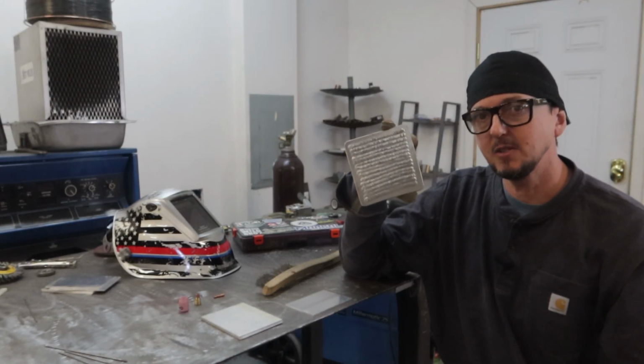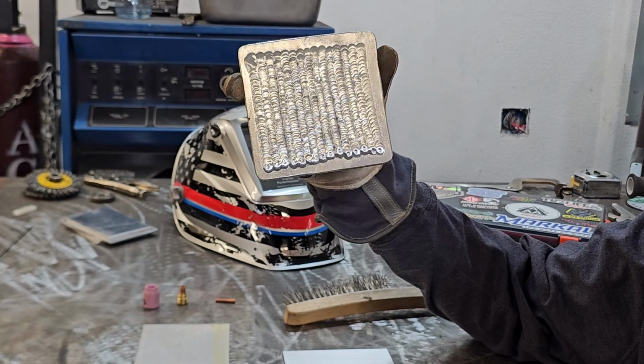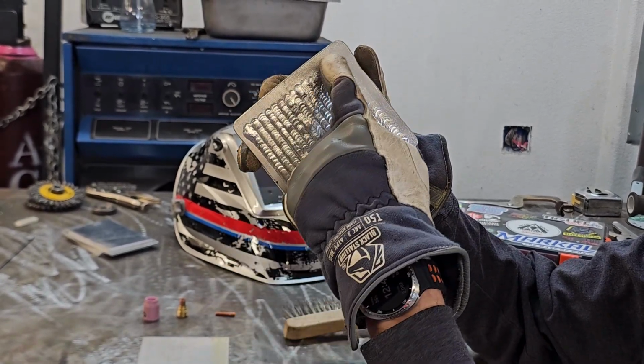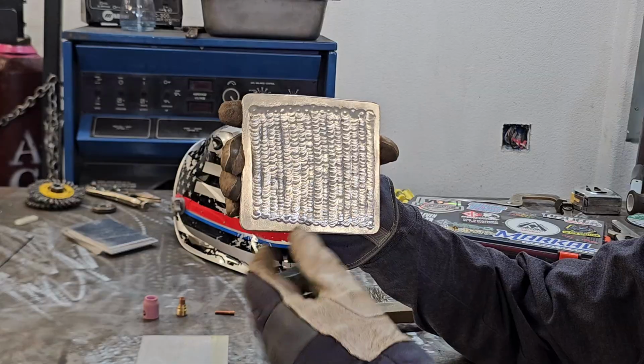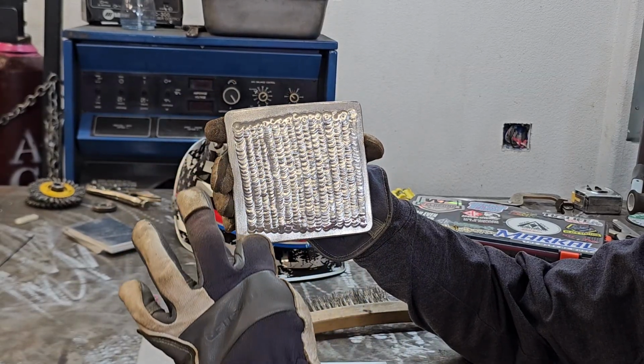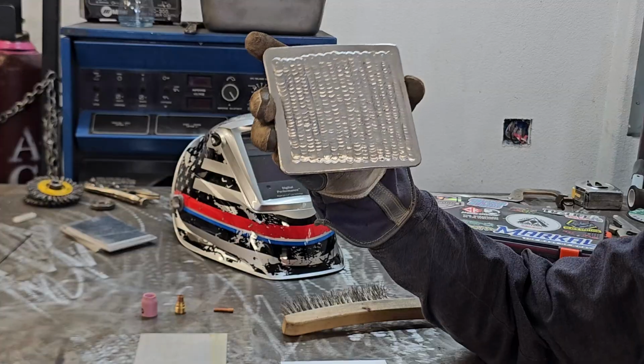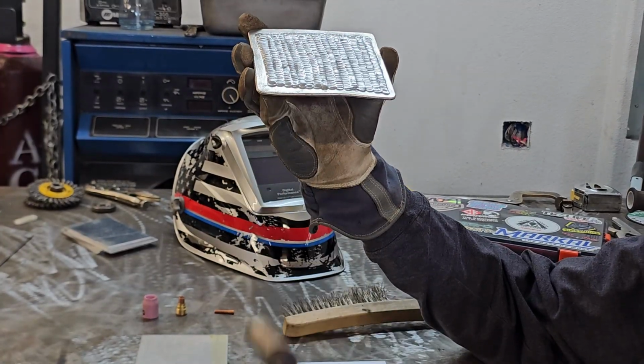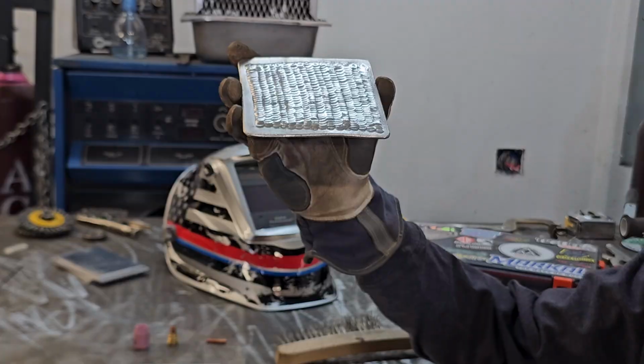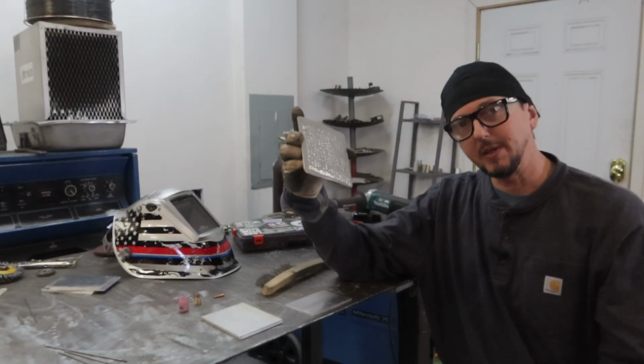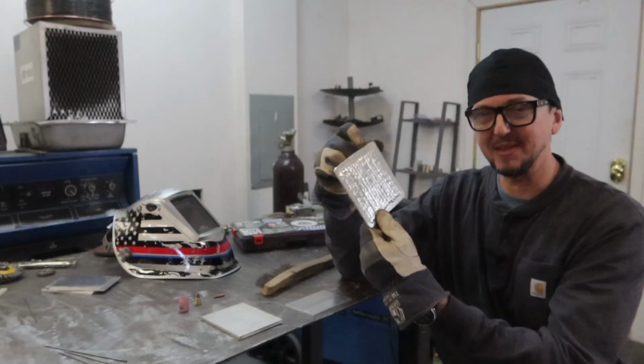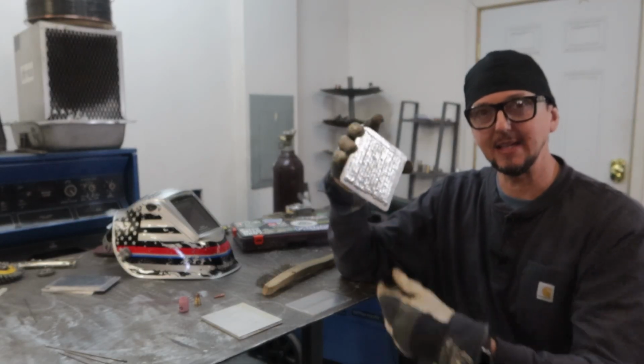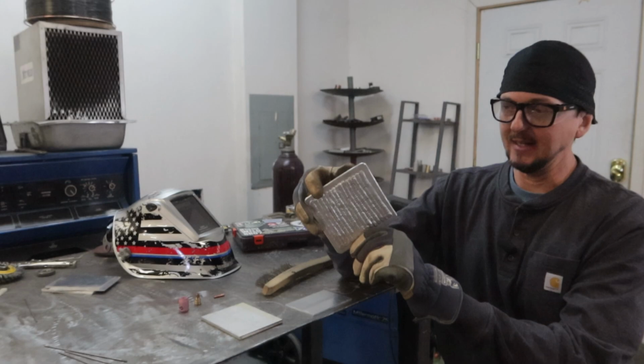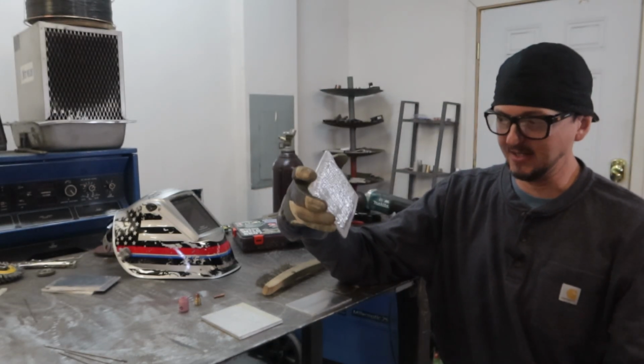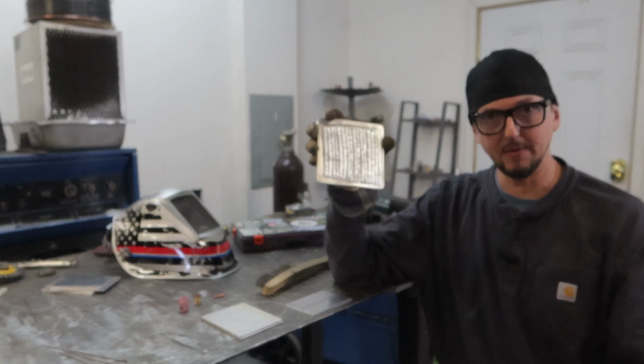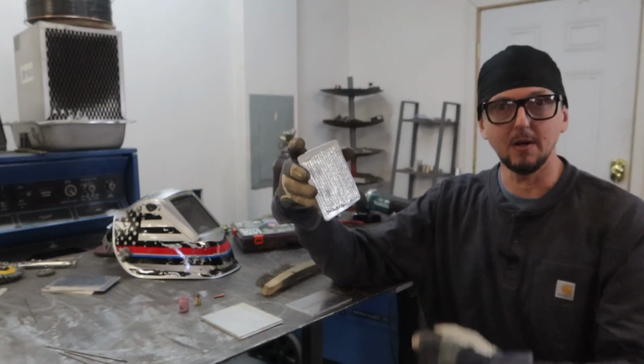these surfacing beads onto our plate. And the thing that I wanted to point out is that you notice from mine, I have this very distinct border all the way around. We want to make sure that we aren't going all the way and breaking that edge on the border, because that low melting point, if we break the edge of the plate, it's going to melt away that edge. And there's nothing really wrong with that, but if you want to be left with a nice piece that you can keep, and something that is appearance-wise nice, you don't want a bunch of edges blown out on your plate. So keep a border all the way around that.